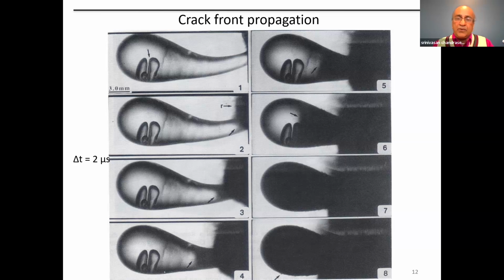Now, what can we learn from this? The main thing is that there's a crack front advancing. Eventually, the fracture front propagates all the way to the left. By measuring the distance between frames and knowing the time interval between frames, we can get the velocity of motion of the fracture front. What we found was that this fracture front advances at just under 2 kilometers per second, about 1,700 meters per second. For reference, the velocity of sound in air is about 300 meters per second.